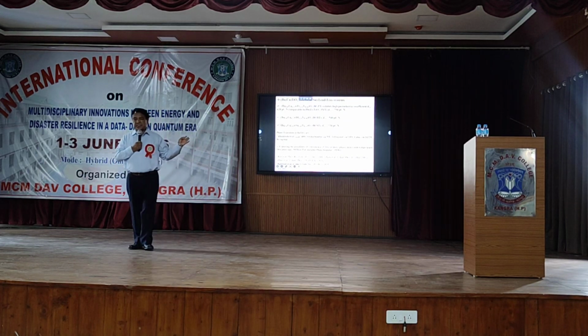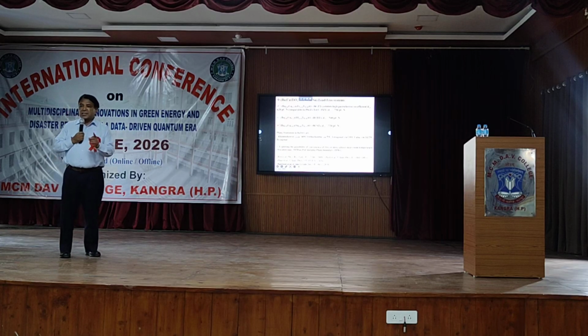Another most important aspect regarding these materials is the morphotropic phase boundary, which I have mentioned here, or a polymorphic phase boundary, meaning that if we have a system having two or more of those phases, which I discussed in the previous slide, in a single material, then we call it a morphotropic phase boundary structure or polymorphic phase boundary structure. The uniqueness of such a structure is that in a system having this type of phase boundary, polarization instability is large. That is, polarization energy is shared by all those crystal structures. So on applying an electric field, on varying the temperature, on varying the concentration, one can easily tune the polarization value so as to have an enhanced polarization value.